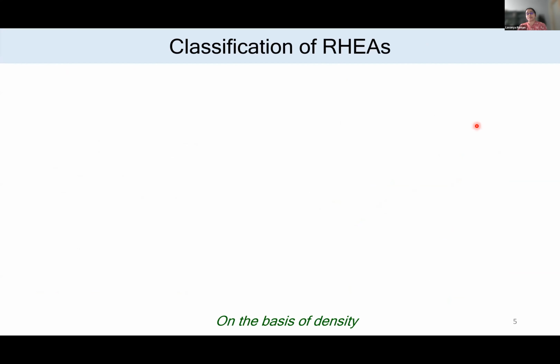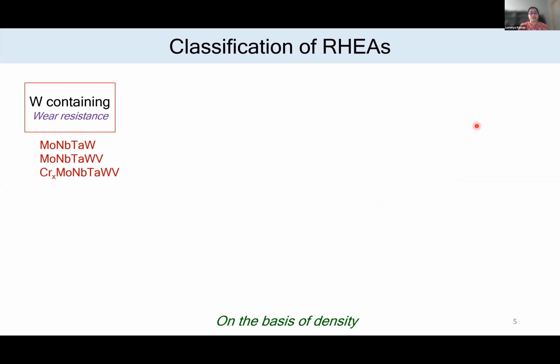Now in the refractory HEA community, there are so many alloys which have been developed so far. I have tried to classify these alloys based on the density so that it will be easier for us to identify the domain which we want. The first and foremost alloys developed in this field were tungsten containing, mainly moly, niobium, tantalum, tungsten, with some vanadium addition, and then there were some modifications. The main intention of this study was to make alloys which can retain the strength at temperatures above 1200. In the study, they showed that up to 1500 it can retain the strength.